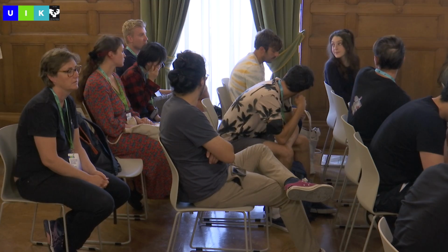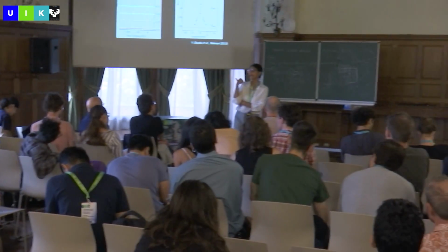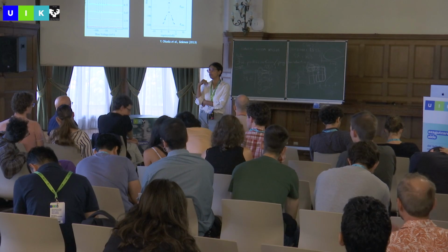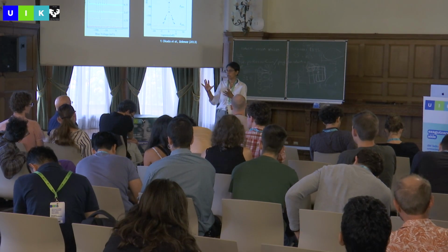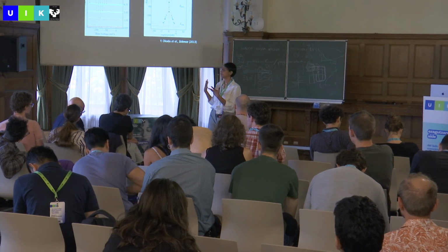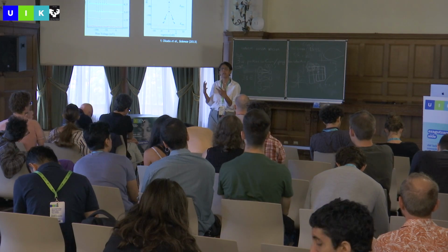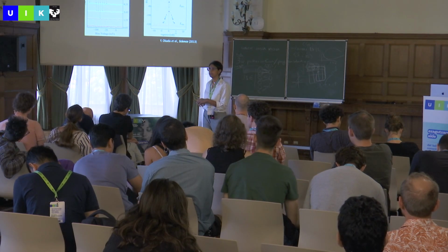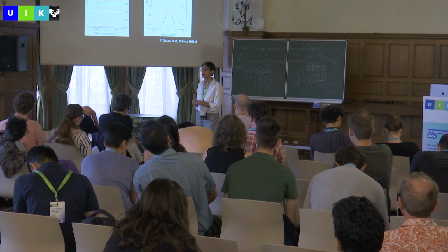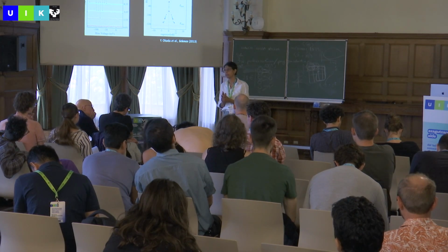So at this ratio of tin to lead, I guess the band gap is very small. So does this influence the measurement? The band gap is actually, at this particular ratio, big. It's, for us, big. I can't remember, 40, 50 meV. Oh, no, more than that. It's about 70, 80 millielectron volts. A 70 millielectron volt band gap is pretty big.